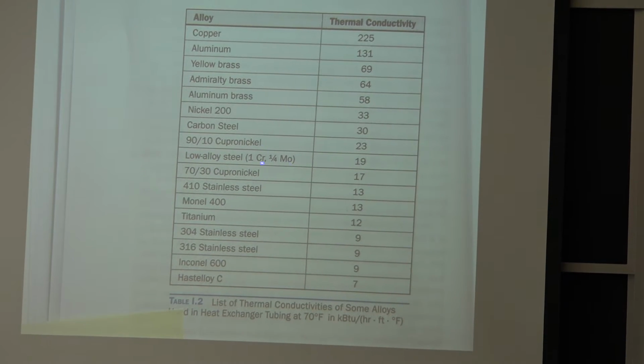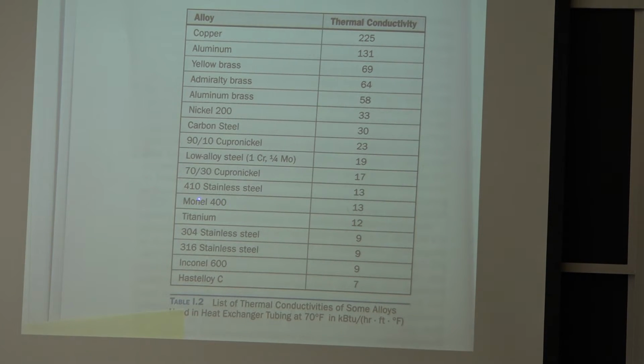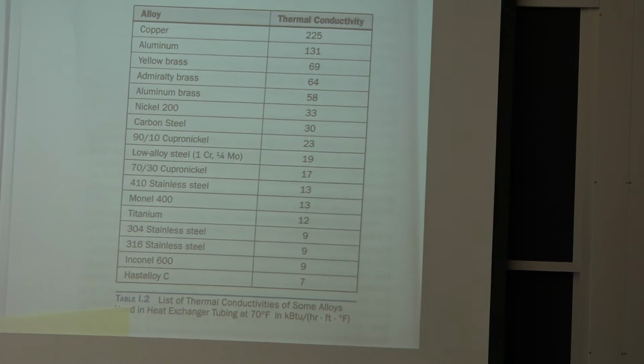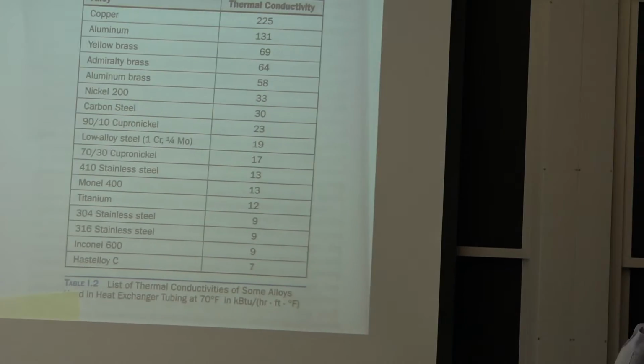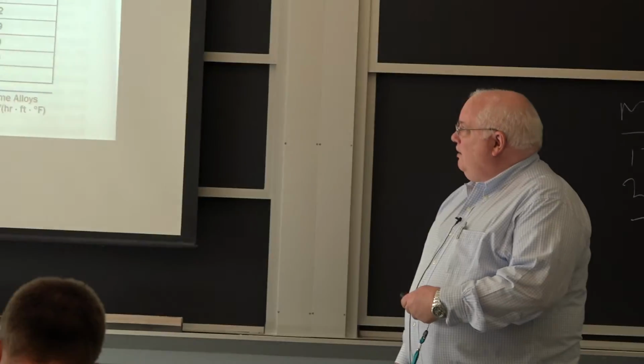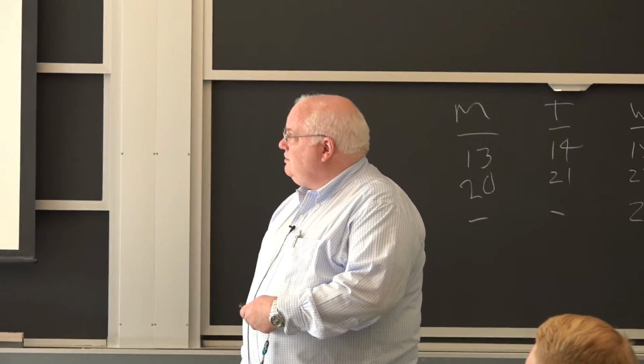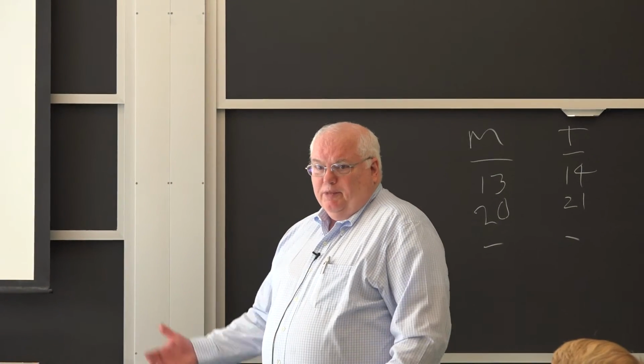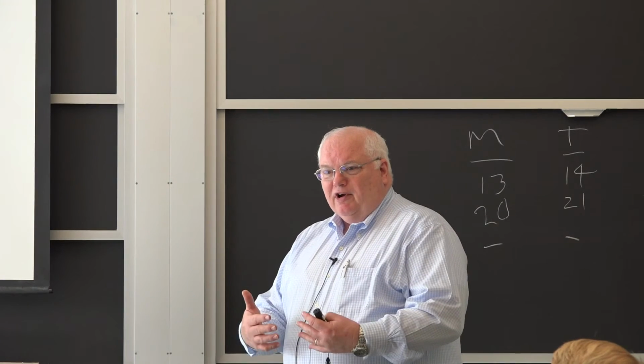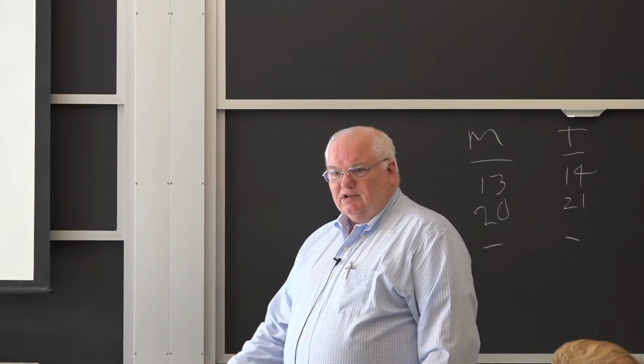For layman's terms, what is cupro nickel? Cupro nickel is just copper nickel alloy. Okay, sorry, it's 90% copper, 10% nickel. Okay, and the Monel 400 is 30% copper, 70% nickel. So if you go across the copper nickel phase diagram, you got 90-10, 70-30, 30-70. The Navy uses lots of Monel in their seawater piping. Good corrosion resistance. Not fantastic. I told you the story about the aquarium. Stainless steel wasn't good enough. Monel was somewhat intermediate in maintenance and everything else. And titanium would have been the best, but it's pricey. So it's a complete trade-off there between price and performance and maintenance and things like that.